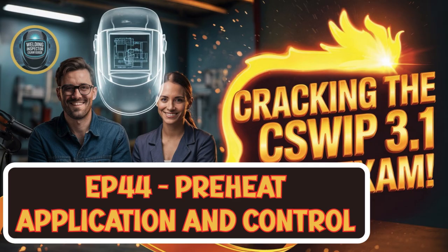Right, the HAZ. So this slower cooling significantly reduces the risk of hard, brittle microstructures forming in that zone. Okay, so it's like letting something cool down gently instead of shocking it with cold so it doesn't become fragile. That's a great analogy, exactly. And this gentle, slower cooling rate gives any absorbed hydrogen more opportunity to diffuse out, to escape the weld metal before it gets trapped as it cools. I see. And that process dramatically reduces the potential for cracking, specifically a type often called cold cracking or hydrogen-induced cracking. Okay, so slower cooling equals less brittleness, less hydrogen cracking.